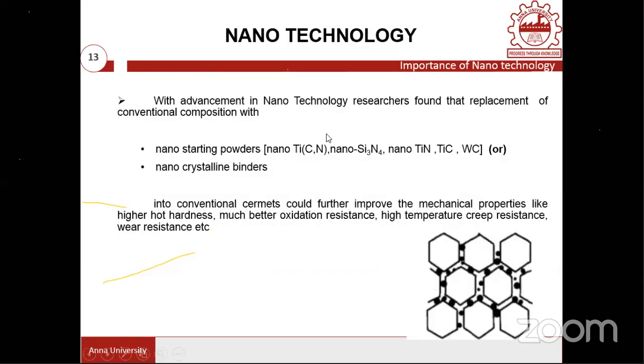Okay, and nowadays, because nano is basic stuff, people take it into account in their research activities. You can also add nano starting powders, but it should not be a completely nano composition of every element. Probably you can have a few elements, the secondary carbides, as a nano starting material, not the primary material as a nano material. Otherwise, you will end up with coreless kinds of structures where the hardness won't be improved. Only the toughness value will improve. Therefore, nano starting powders can be recommended only for secondary carbides, which will be uniformly distributed in the inner rim as well as the outer rim, but the core remains unaffected.